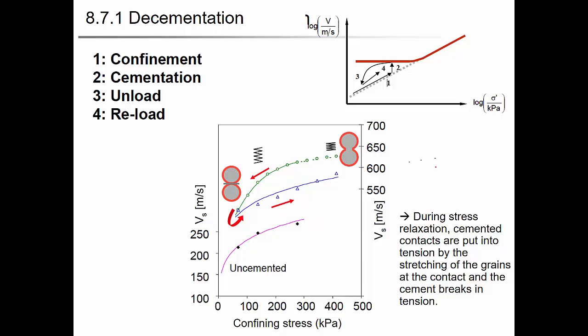So one interesting thing is that when you apply the cementation under high stress, it's different from when you apply the cementation at low stress. So this is the case where you apply the cementation at this location. I think in the uncemented case, it's going to be like this. And then at this high stress condition, around 400 kilopascal, the cementing agent has been cured, so you have increasing shear velocity about this. Right? So the soil was compressed initially when the cement gets cured.